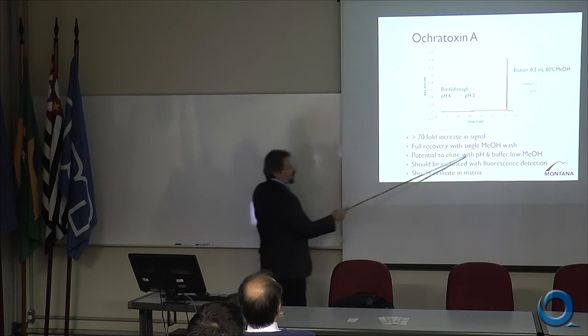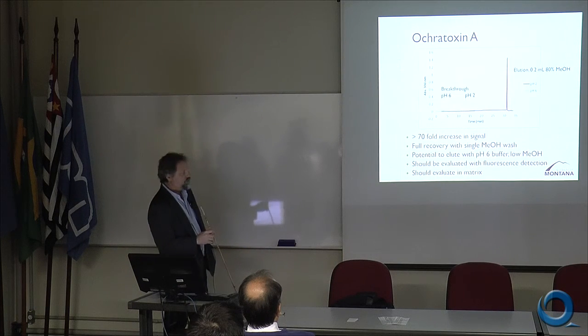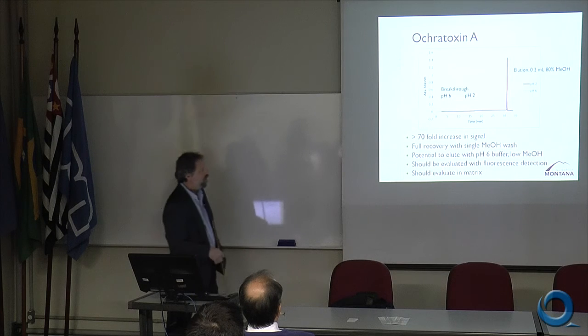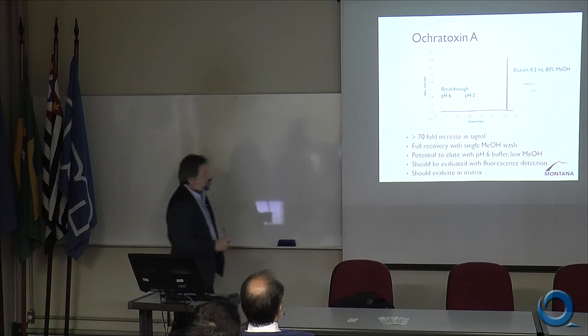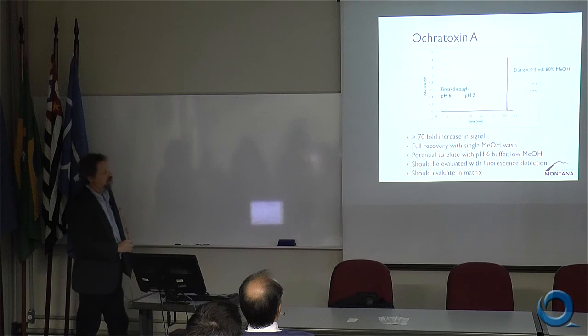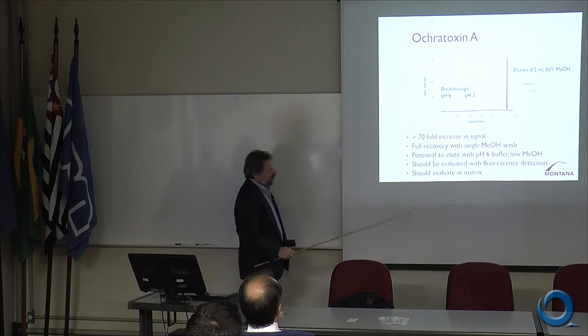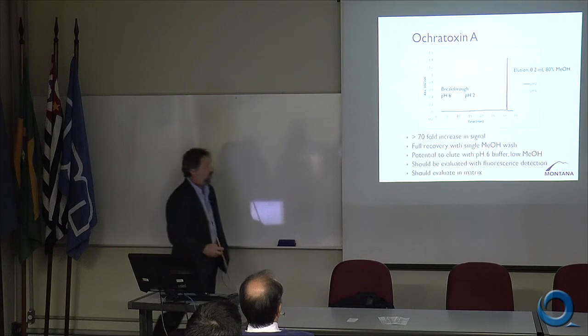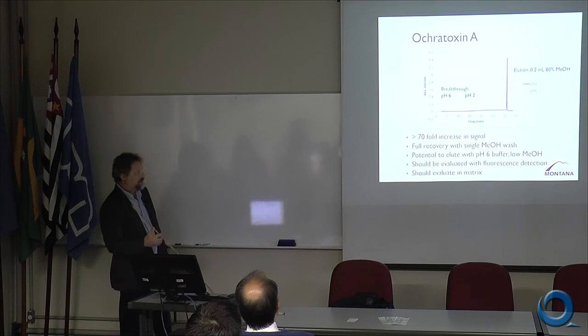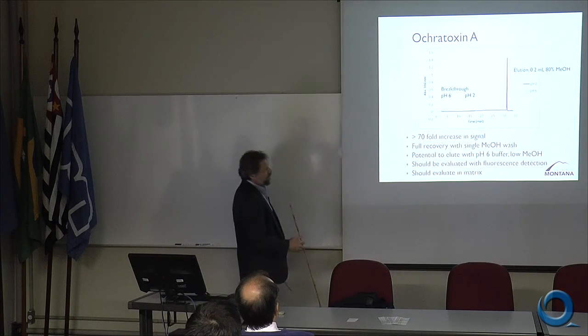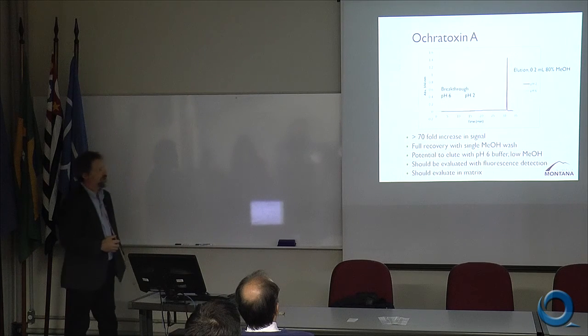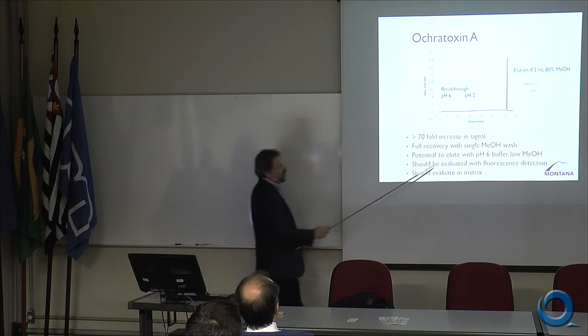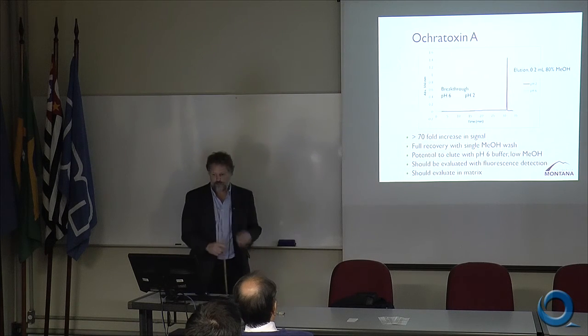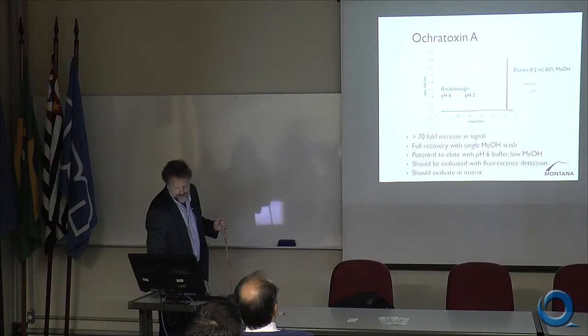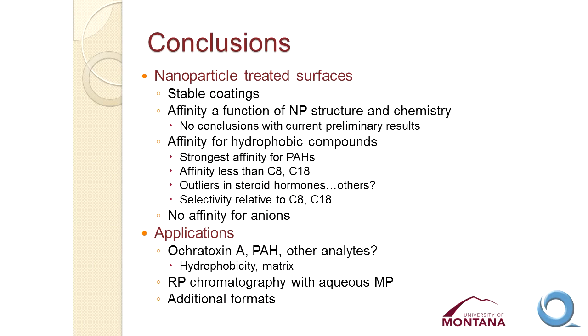So there is the potential to elute this molecule in a pH 6 buffer at even lower methanol concentration. This approach could be evaluated with fluorescence detection to see just what kind of concentration you would be able to detect. And it should, of course, be evaluated in the matrix of interest. One of the matrices for this analysis is wine, and wine is already 10, 12, 14% ethanol, so it's not clear just how much retention you would get due to hydrophobic interaction from wine, but that's something that would need to be evaluated.